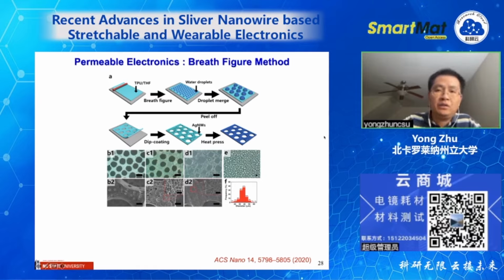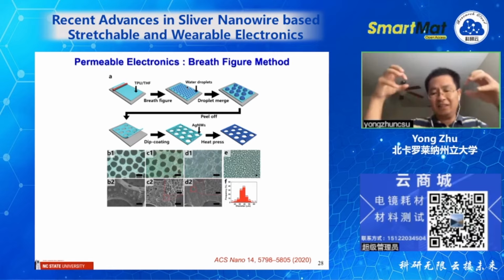There are different ways to do this. We use the so-called breath figure method. This method is very simple and easily scalable. Essentially, we have TPU, this time with a solvent called THF. We coat a film, and then we put it in a very humid environment, and the water will condense.